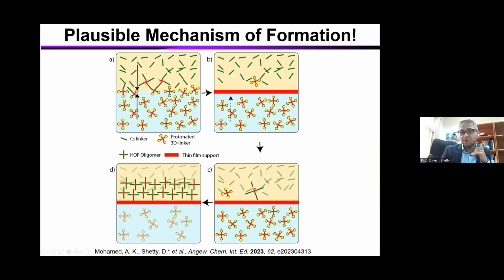What is happening, to our understanding? In the beginning, there is a free flow because there is nothing in between these biphasic systems. So they can meet each other. They can start to react fast. The kinetics is fast. Usually when you want a framework structure, you have to reduce the kinetics. So then the COF film is formed. Once the COF film is formed, you have a barrier between these biphasics. Then the diffusion of this building block is controlled, right?